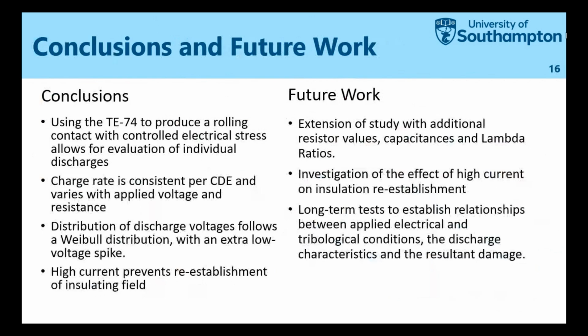So with all that entertainment out of the way, what conclusions have I drawn? Well, at the very least, I can use the TE-74 to create a good rolling contact with controlled electrical stress for the evaluation of individual discharges. The charge rate's consistent for each discharge event, and it varies as expected for applied voltage and resistance. The distribution of discharge values follows a Weibull distribution. What that extra low voltage spike represents, I'm not sure.